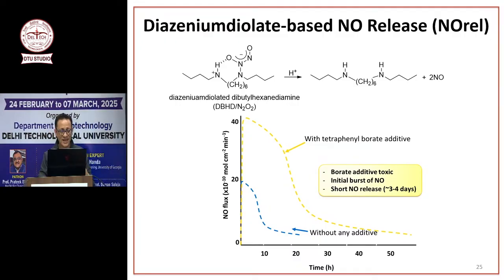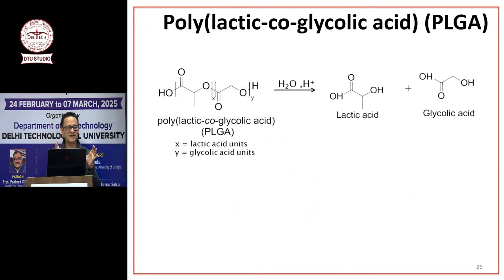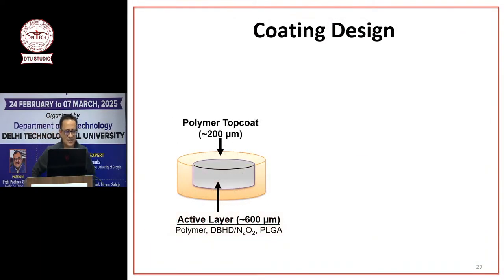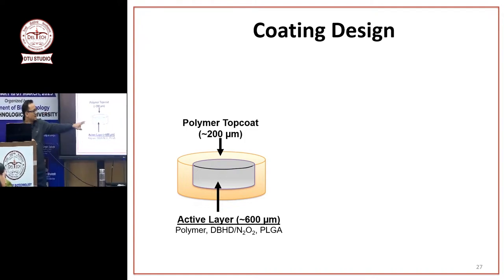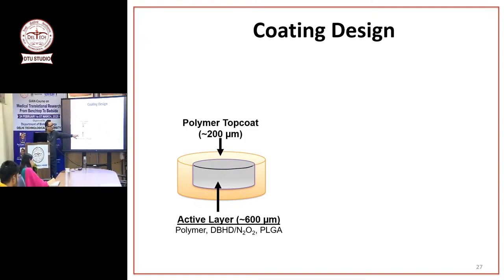Okay. I'm showing you about two years of work, but thinking is one thing, making it happen is another thing, and finding the right PLGA is another thing. So there is a lot of optimization. We designed our coating, and let's say we use polyurethane. We tried a lot of different polymers: PVC, silicone rubber, polyurethane. But let's say polyurethane. So we made a polyurethane film. We added polyurethane, diazeniumdiolate, and PLGA in it. But then we put a top coat of only polyurethane.